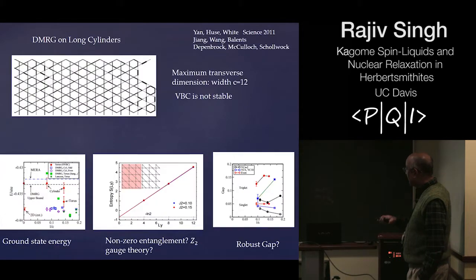So let me just quickly flash this thing on DMRG studies, which has been very important. Basically, DMRG is a method meant for studying one-dimensional systems, but they have also succeeded in studying two-dimensional systems, basically by considering it on a finite cylinder, by essentially considering the two-dimensional system as a one-dimensional system with some longer range interaction. And the thing that they find, first of all, is that the ground state energy, the claim is that the ground state energy does not have much size dependence. This C, let us say, is the transverse direction over here, which is limited. They cannot do much bigger than 10 in this direction, or much bigger than 12, which is like 6 unit cells. But the claim is that there is not much size dependence to the energy over here,